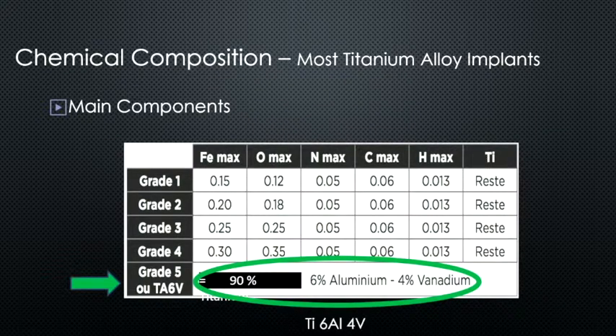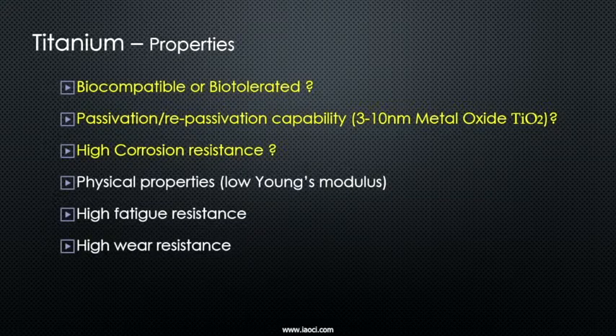So let's look at the composition of titanium first of all. Like I said, 90% titanium, 6% aluminum, 4% vanadium. Now, what we're told, or have always been taught, is that titanium is biocompatible. Now we have to ask ourselves, is it biocompatible or biotolerated? But that's a debate that we can have. That it can develop an oxide layer. Studies are now showing that in the process of inserting that implant, that oxide layer usually gets wiped off the implant. We were always taught that titanium is one of these materials that never corrodes. There's tons of literature, old and new, that shows that there's a corrosion problem with titanium.